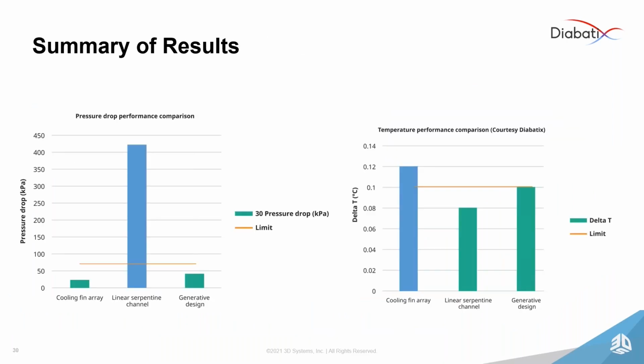And if we summarize all three of the results, you see in terms of thermal gradient, the serpentine design and the generative design were performing well, while the cooling fin array was not good enough. If you evaluate the pressure loss, you see the opposite. Well, the generative design is still performing well. The cooling fin design also, but the serpentine design had a way too high pressure loss. So to conclude, generative design is solving all of the design constraints here, which was not possible with the conventional way of designing. So that's for the design part.